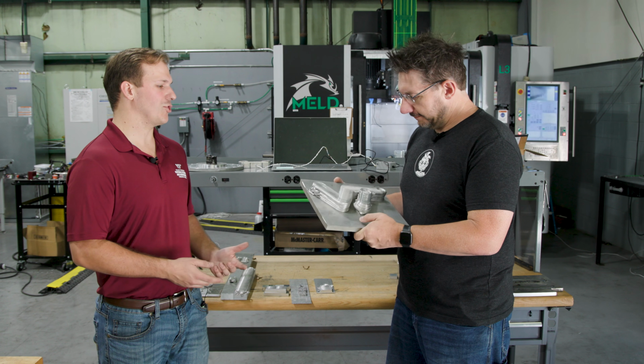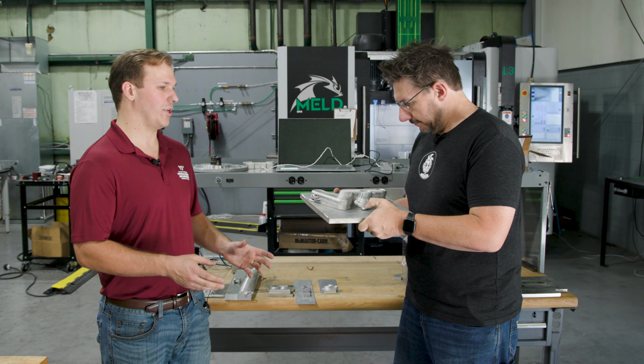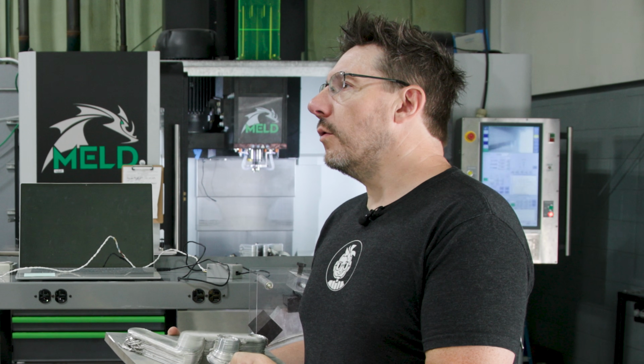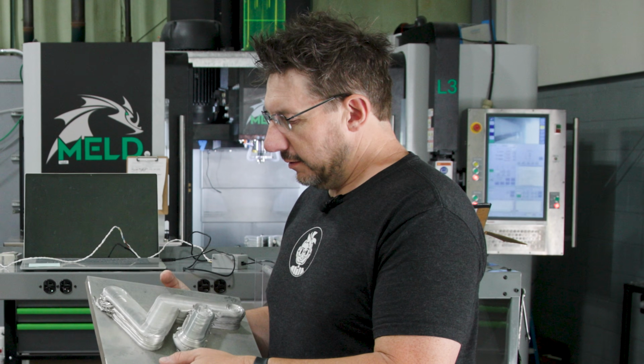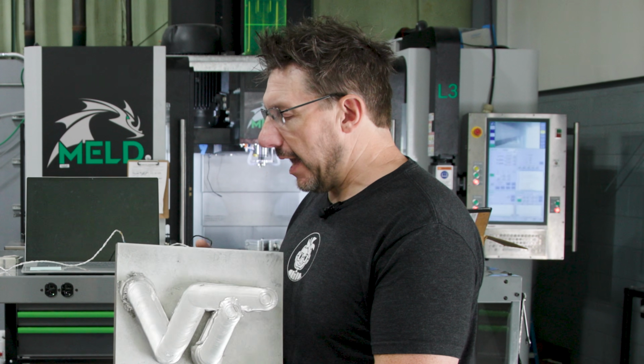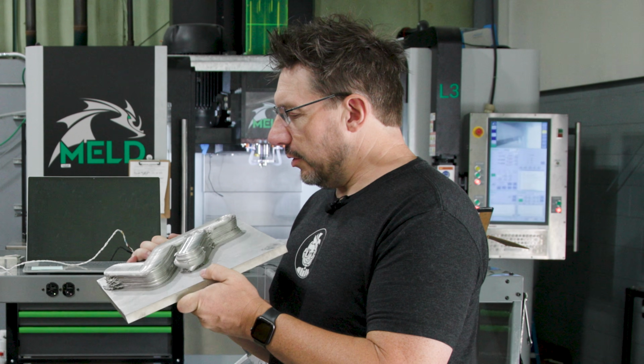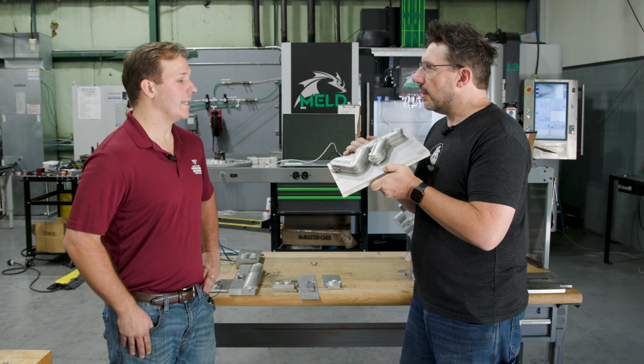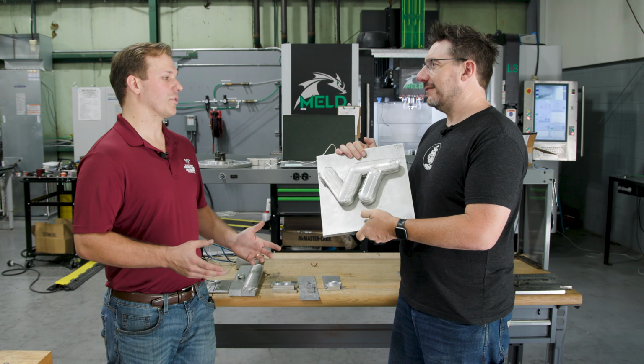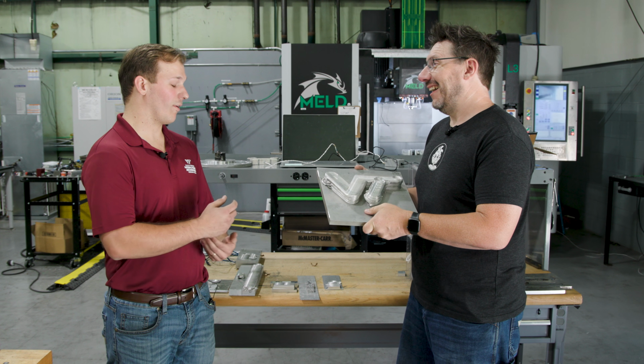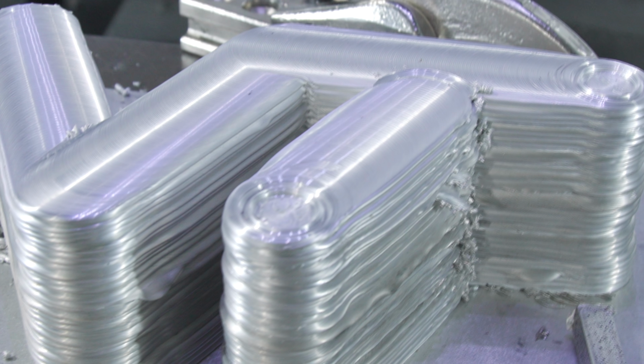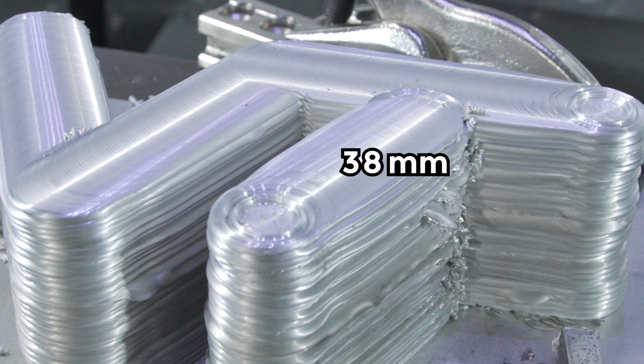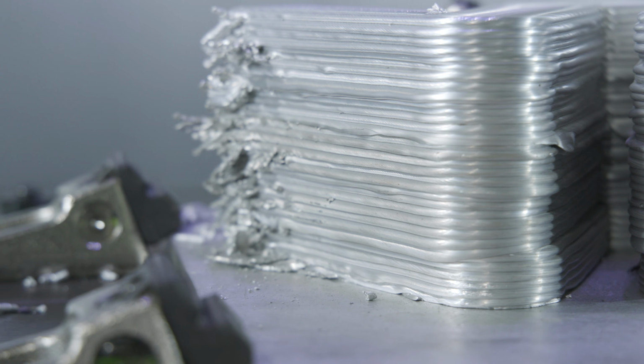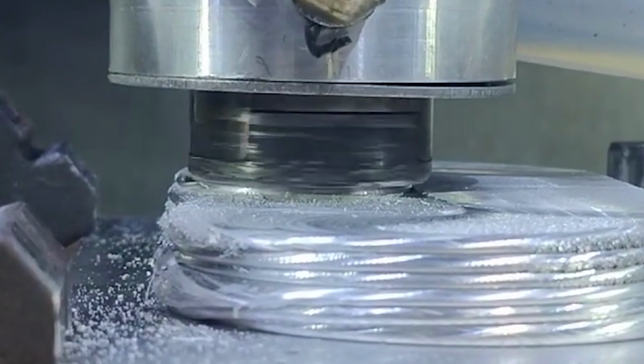So we're not really changing anything in the workflow of how you would go through the manufacturing process. In other additive processes, you're still creating near net shapes and having to machine them to a final spec, but here you're making this size part really fast. Our feature size is very, very large. Our print volume is about 38 millimeters wide and 2 millimeters thick, so we're volumetrically depositing massive amounts of material.